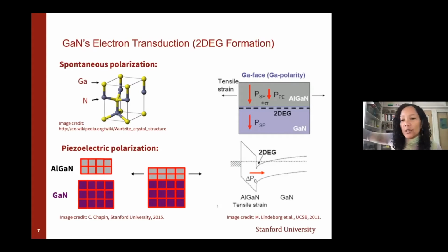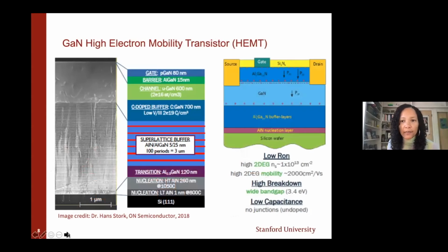this two-dimensional sheet of electrons. And this is how we transduce. This is the conductive channel that we can manipulate with external stimulus or our gate, changing the sheet density, et cetera. And this is a very high mobility or fairly high mobility channel. And you can see again this quantum well forming due to these two effects. So this is different from a doped silicon junction. We have this two-dimensional nature, which I find interesting because that can get around certain bulk scattering effects, which can really impact high temperature behavior.